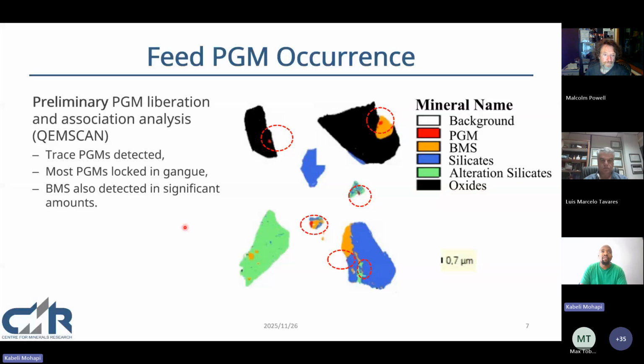We performed some preliminary PGM liberation and association analysis, and in it we were able to establish that there's a significant amount of PGMs that remain entrapped and encapsulated within the gangue minerals in the feed, which explains why they were found in the tailings in the first place. There's also a significant amount of base metals, which are also valuable, and we'll be looking to recover those. This further confirms the potential benefit of grinding further to improve liberation prior to flotation.